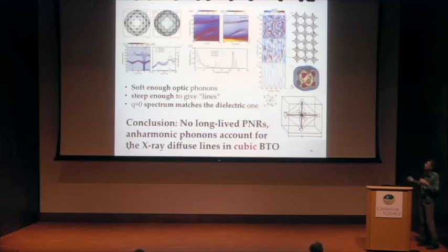It's something which has a time constant of typically a picosecond. We can also look at the position histogram of the displacement of titanium, really in the cubic phase at that temperature, which is 100 Kelvin above TC, I forgot to say. There are 8 positions which are more probable, like the most probable positions of the titanium.